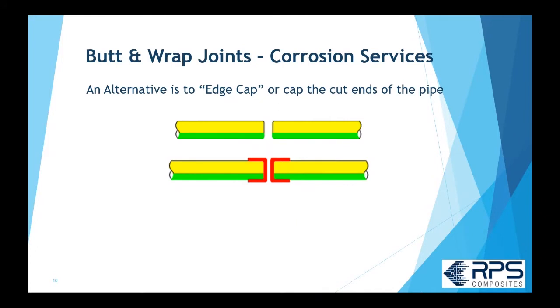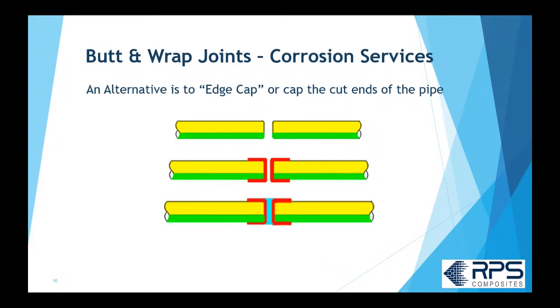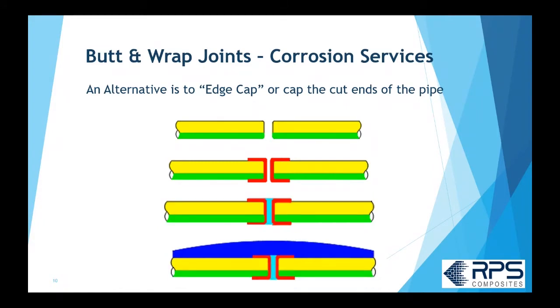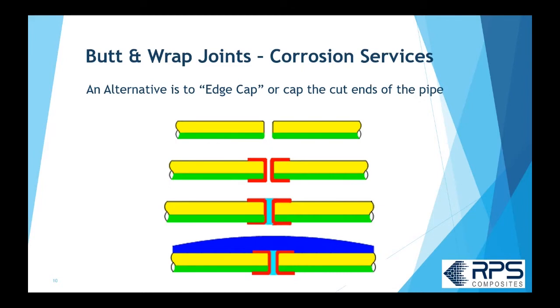In this case, the red lines I've laminated right from the inside to the outside and wrapped it right around the pipe. Sometimes it's just a layer of surfacing veil. And sometimes in more severe services, it's the full corrosion barrier that I've put over the edge of the pipe. I then put on my crevice paste and do my laminate as normal. And basically I've protected that edge of the pipe back maybe a half an inch or an inch as well. And this is a common way to give you a bit better corrosion protection with the butt joint system.